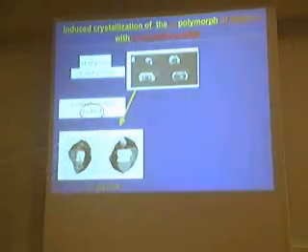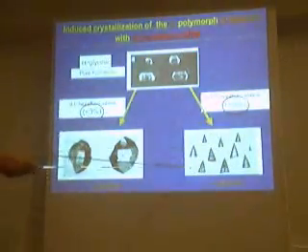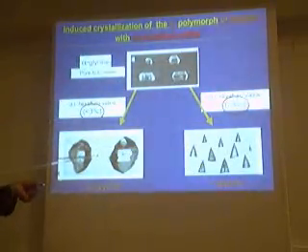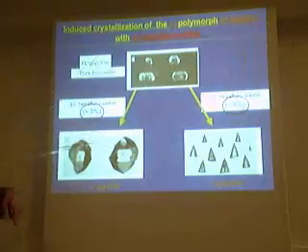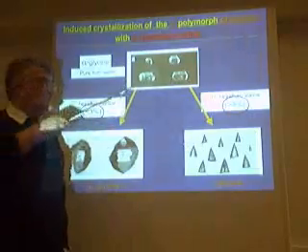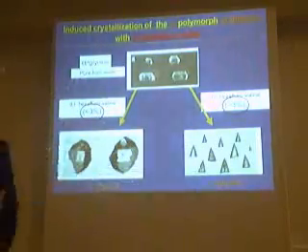Instead of these bipyramids, you're getting crystals where these sides are completely inhibited. But if you go beyond 3%, what happens is you get to the gamma phase, which means the DL inhibits not only the growth of the crystal, but the nucleation of the alpha form. And it doesn't interfere with the growth of the gamma form, and therefore you can really grow the gamma form. And we have done some experiments recently where we can inhibit both the alpha form and the gamma form, and we get the beta form, which is the metastable form of the system.